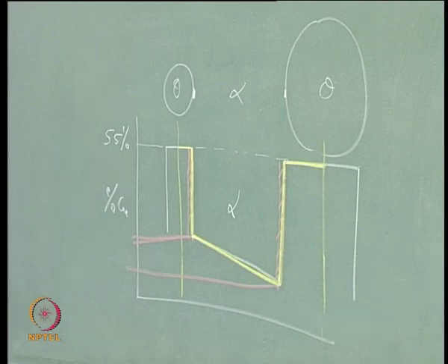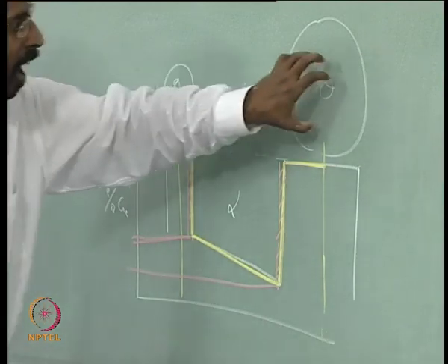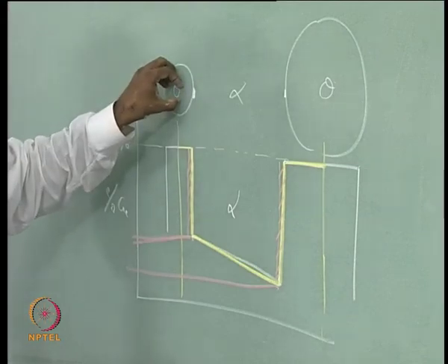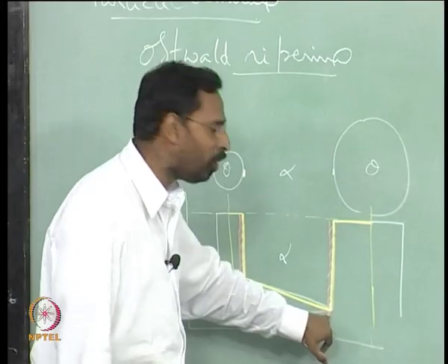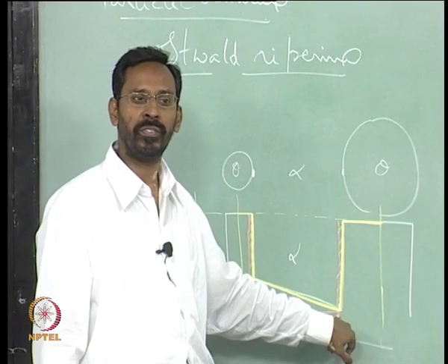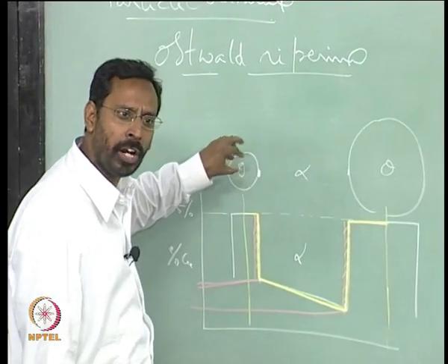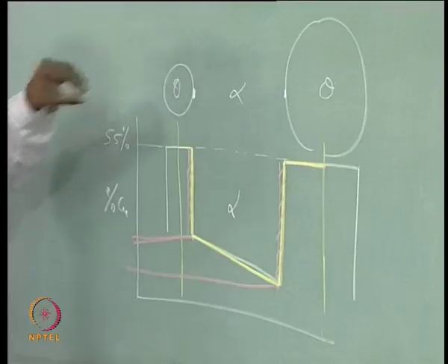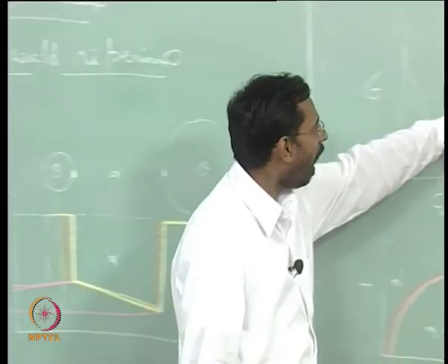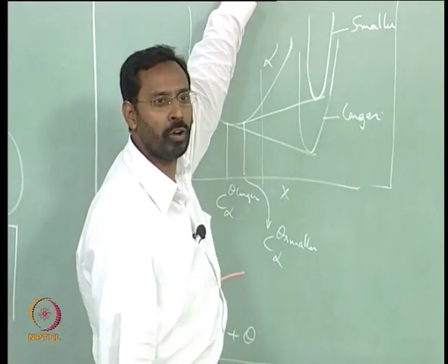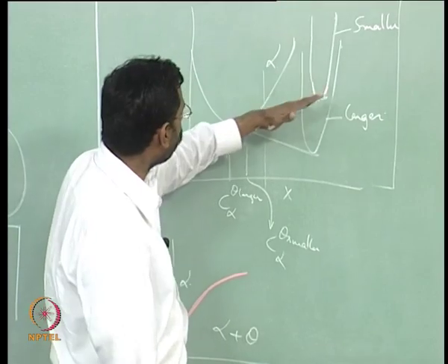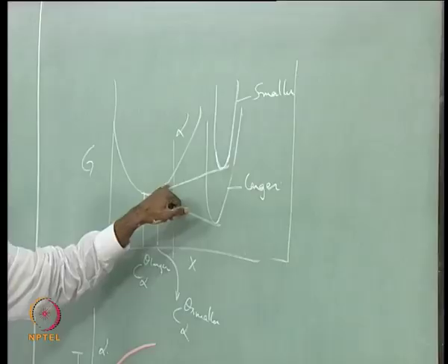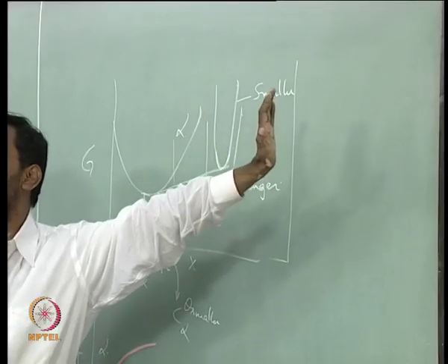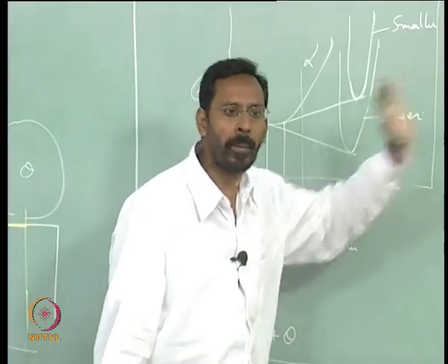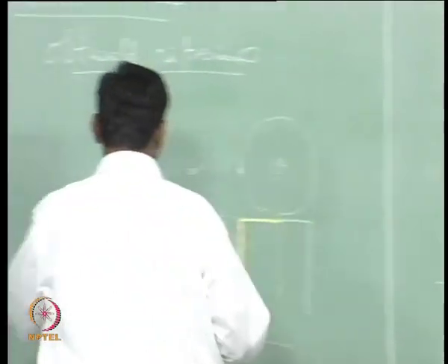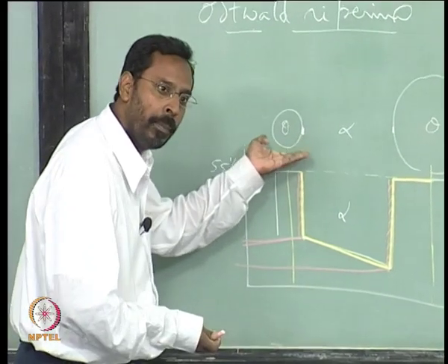Radius. So, as the radius of these two change, in principle these two values also will change. As this particle becomes smaller and smaller, as it shrinks, what happens? You can see as this particle shrinks, this free energy goes up. If this free energy goes up, the common tangent starts touching it at a composition which is higher in copper content. So, that means you would see that this value keeps going up.